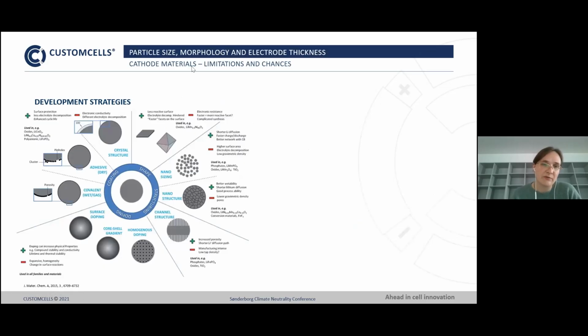This is a chart for mainly cathode materials, but it also holds true for some anode materials, that there can be nano sizing of the materials or channel structures that direct volume changes into a certain direction. Furthermore, you can have a core shell gradient, especially for cathode materials with high nickel content, where there is the highest nickel content in the middle of the material and the lower nickel content on the outside, so that the water sensibility is reduced. Surface treatment with adhesive dry methods or wet coating can help to prevent further reactivity of the materials.